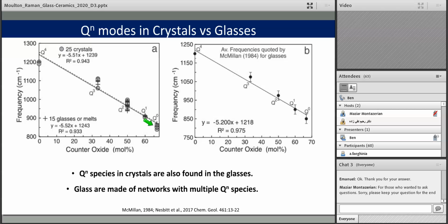We mentioned a similarity earlier, but let's look at some crystals and an early correlation from 1984 that compared the intensity of the main feature in crystals where the structure was known, Q4, Q3, Q2, Q1, Q0, and compared it to glasses, the most intense peak in the glasses, and they found that both crystals and glass have a very similar behavior. They're combined into this relationship here, where the frequency decreases as the number of non-bridging oxygen increases, and the separation between these frequencies decreases as well.